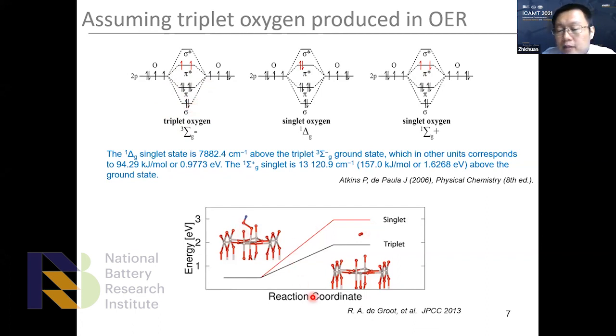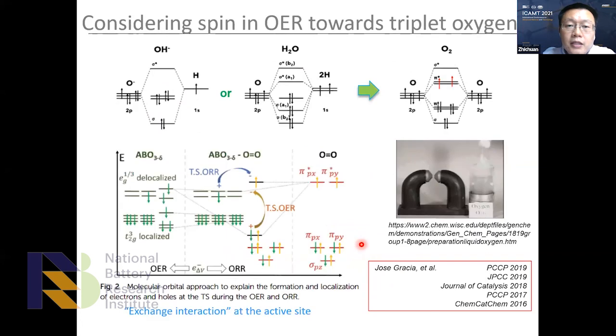So there is some modeling work that has predicted that in the oxygen evolution reaction, at the last step, if we release a triplet oxygen, this will be much easier than releasing a singlet oxygen. The energy difference can be more than 1 eV. So now, this actually recalls the early modeling prediction by Jose Gracia.